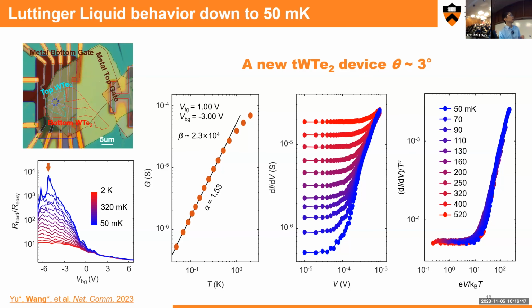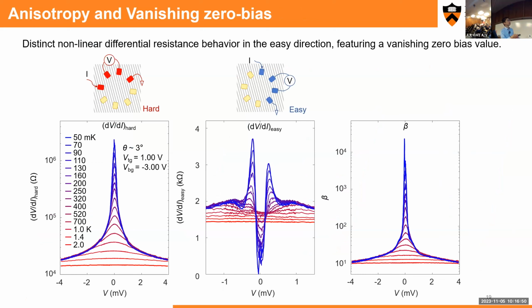Yeah. So in our situation, we can actually measure along another orientation, and along the other orientation, it didn't show similar behavior. It shows very, very high resistance. This is the first indication of the superconducting phase. Along the easy direction, it shows superconducting-like behavior, but along the other orientation, where we just rotate the contact on the device and send the current across this geometry, the resistance goes very high.